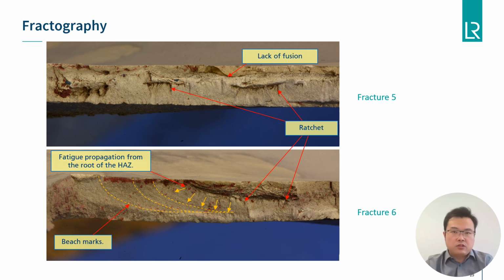Similarly, in fracture parts 5 and 6, there are similar positions and morphology of ratchet marks and beach marks, all of which indicate that the fatigue propagation of the crack started from the root of the heat-affected zone from the welding, and it is definitely related to the lack of fusion during welding.